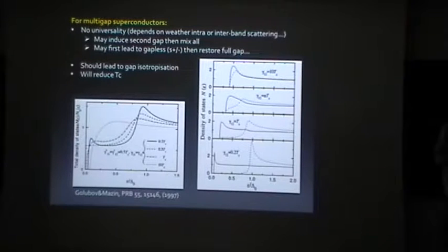About the disorder problem in the pnictides, I wonder if you agree that you mentioned one aspect of the difficulty in interpreting experiments with disorder, namely that you don't really know whether a given chemical impurity is causing intraband scattering or interband scattering, how strong it is, etc. There are a lot of parameters. But another problem is that all the theoretical work assumes that the impurity acts basically as a potential scatterer and doesn't affect the pairing interaction. Whereas we know that almost everything we do in the pnictides affects the pairing interaction because it somehow affects the structure, and Tc is very sensitive to this. So I wonder if you have an idea of what the right way is to dope or to irradiate a system in order to create a system with which we can compare theory.